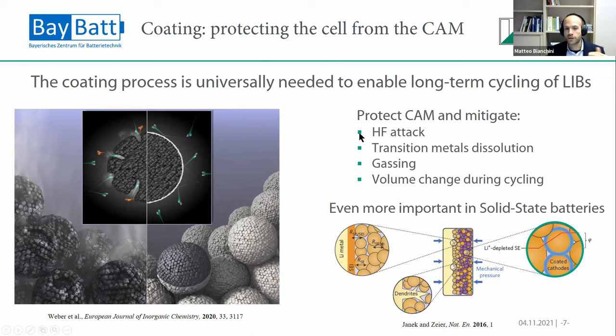And this HF is generated in the cells typically by a small amount of residual moisture that can sneak into the cell. It can help hinder transition metal dissolution. It can help hinder the gassing, so the oxygen evolution from the cathodes at high state of charge. Or it can even hinder, to some extent, the volume change of the cathode material during cycling. So it's really important in order to stabilize these materials.